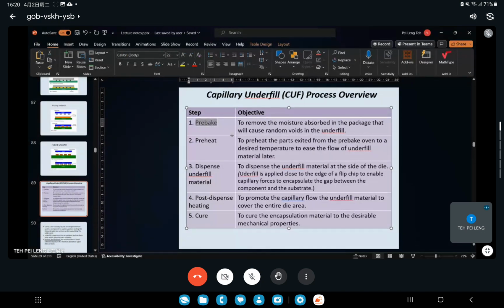Put in the oven to let the moisture evaporate, so that you will not have voids after that. If you have moisture and you put the underfill, then reflow or curing, you apply heat, right? This moisture at 100 degrees will evaporate, so it will leave voids. You will have voids inside your underfill, so this will cause defects. So remove the moisture inside your package first.